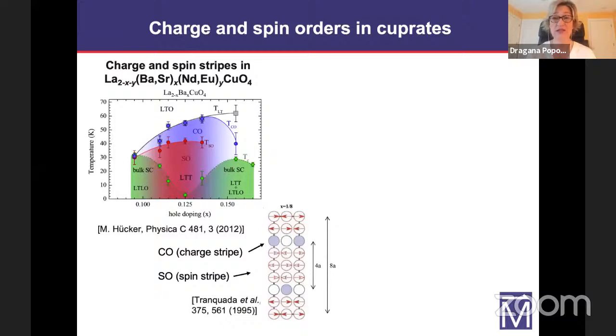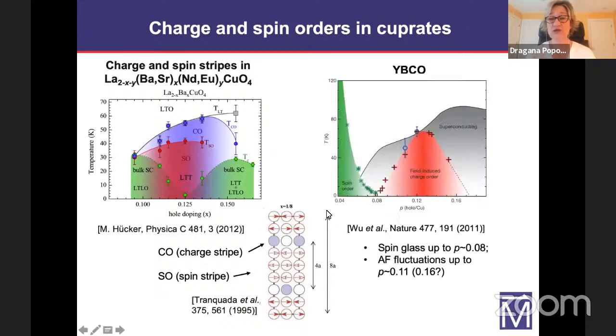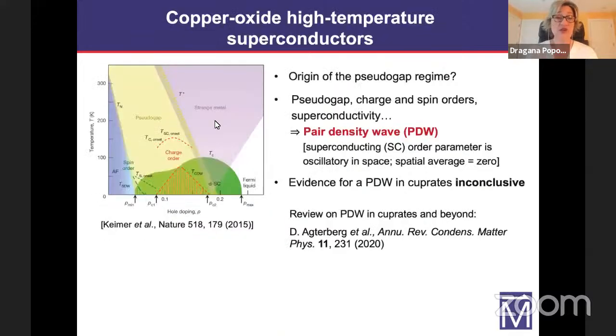Now, in some other materials, such as YBCO, the situation is slightly different. For example, here it is known that charge order is stabilized only if magnetic field is sufficiently high to sufficiently suppress superconductivity. And spin order actually disappears at relatively low doping, so that spin and charge orders in YBCO do not seem to coexist. So in general, this pseudogap regime is known to be unstable towards a variety of ordering phenomena.